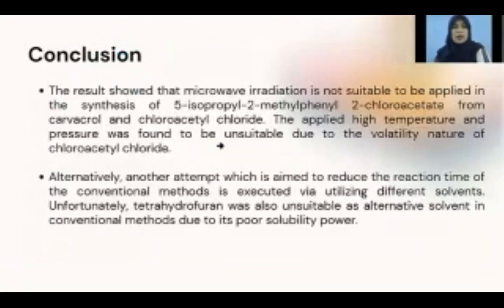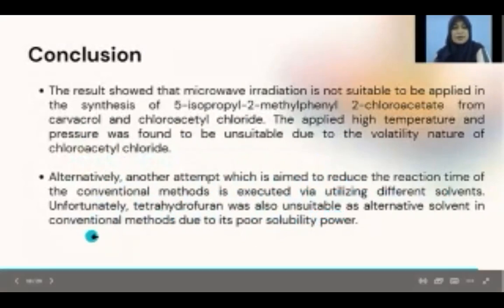The results show that microwave irradiation is not suitable to be applied in the synthesis of 5-isopropyl-2-methylphenyl 2-chloroacetate from carvacrol and chloroacetyl chloride. The applied high temperature and pressure was found to be unsuitable due to the volatile nature of chloroacetyl chloride. Alternatively, another attempt aimed to reduce the reaction time of the conventional method was executed by utilizing different solvents. Unfortunately, tetrahydrofuran was also unsuitable as an alternative solvent in the conventional method due to its poor solubility power.